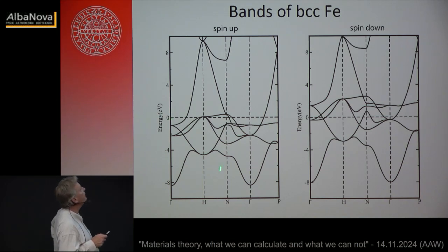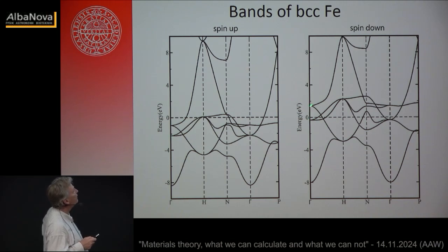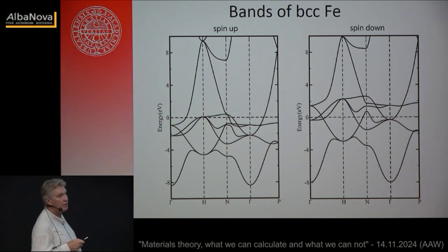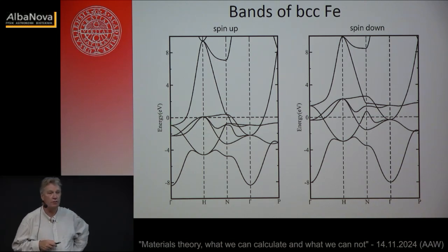And the spin up is here, spin down is here, and there's an exchange splitting. You can see it maybe most easily at the gamma point. These two bands look like so. They are found over here, basically the same symmetry and shape of the bands, but these are now at a little bit higher energy than these guys here. This one is unoccupied above the zero line, and this one is occupied below the zero line. So there's an exchange splitting here of roughly 2 electron volts.